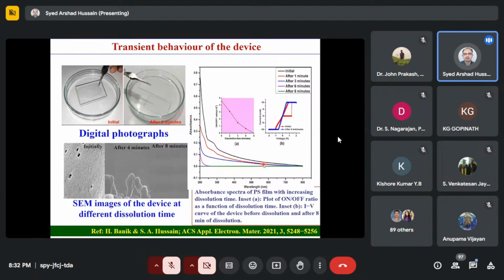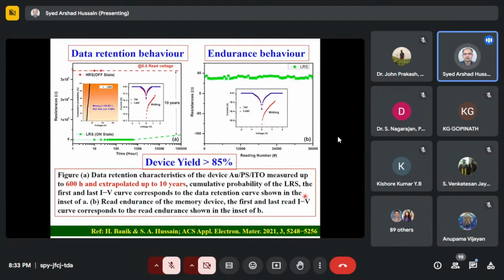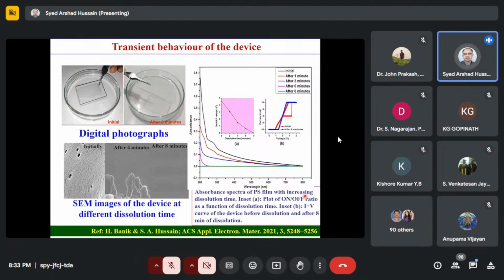Then again, we analyzed the transient electronic behavior of the device, and we found that our device shows transient behavior. But of course, here the time is a little bit more, and we saw that to 100% dissolve the device in water, it took around, say, 8 minutes. Then you see the flat line, and we also measured the IV characteristics. As a whole, the PS-based device is promising for WORM applications with very good data retention behavior, high device yield, and also transient behavior.